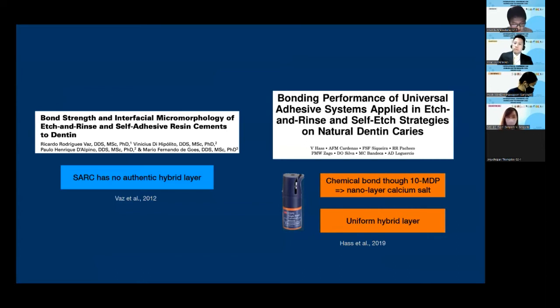On the other hand, self-adhesive resin cements cannot encapsulate the collagen network and form an authentic hybrid layer. So these resin cements adhere to the dentin weaker than the Superbond system. But with single bond universal adhesive coating, it shows almost double the shear bond strength. Hass et al. found that a single bond universal adhesive coating can promote a dense, uniform hybrid layer. Also, 10-MDP in this adhesive can ionically bond to the calcium ion in hydroxyapatite and form a nanolayer calcium salt.